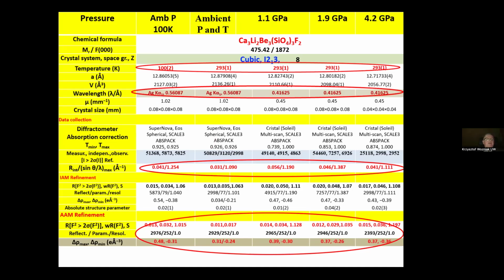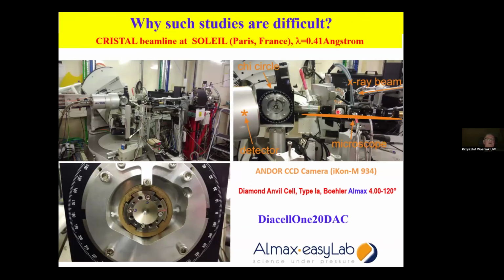We have collected data using our silver source and also other high pressure data sets at Soleil in France and refined experimental electron densities. And it appears that we can refine electron density under pressure measured in a diamond anvil cell equally well as for crystals outside a diamond anvil cell. And that's the setup at the crystal beamline at Soleil.